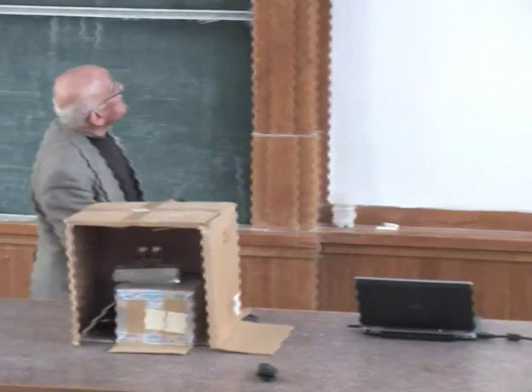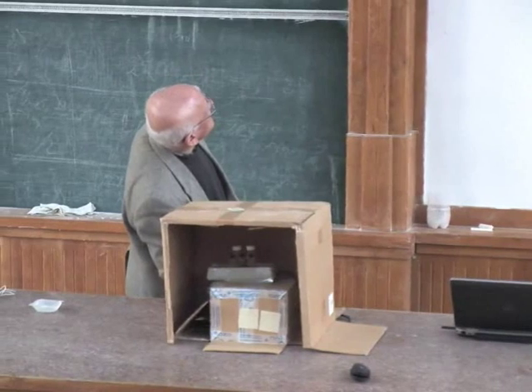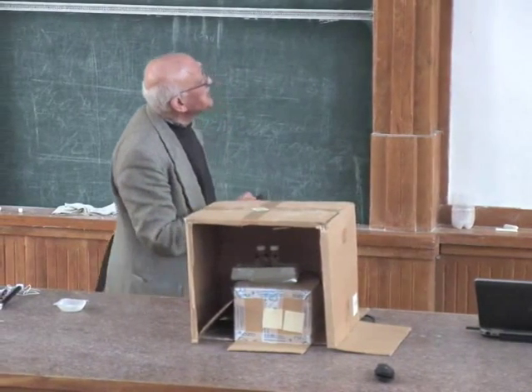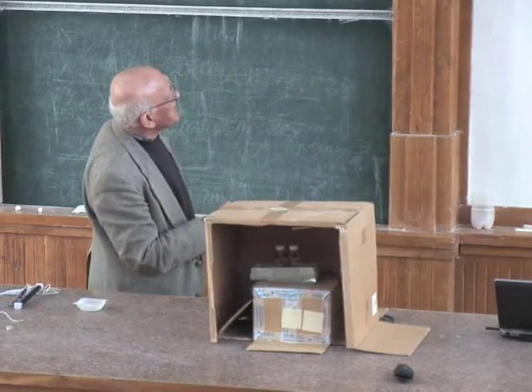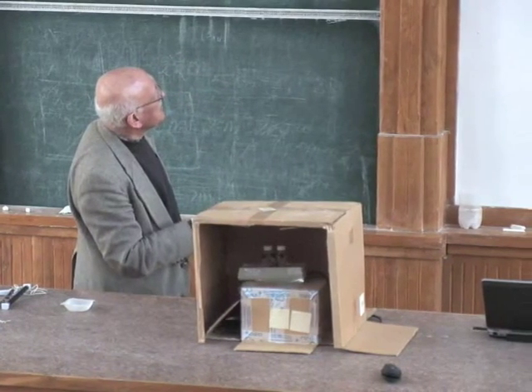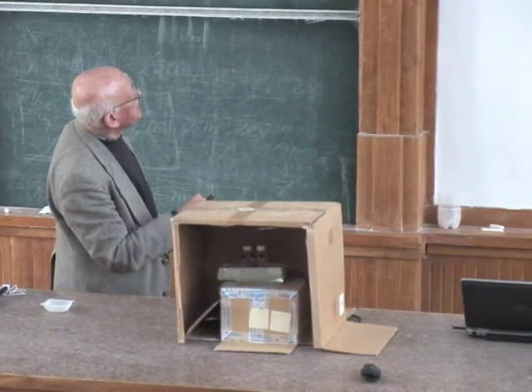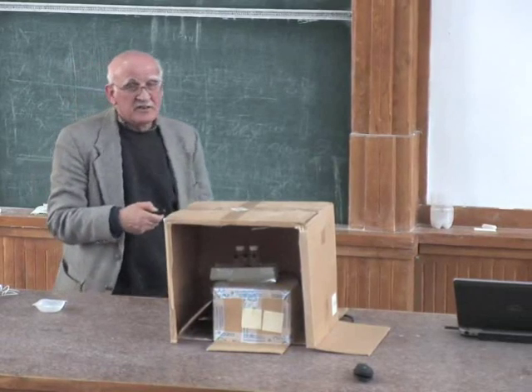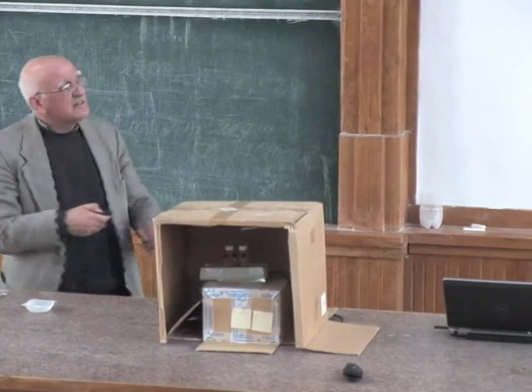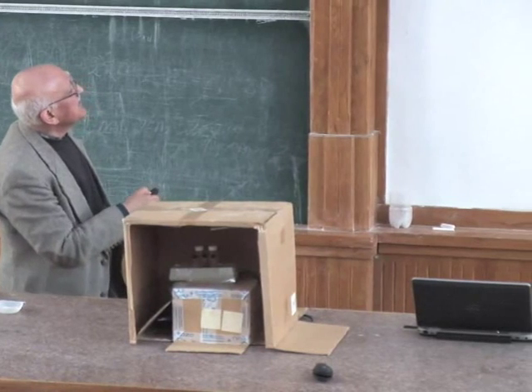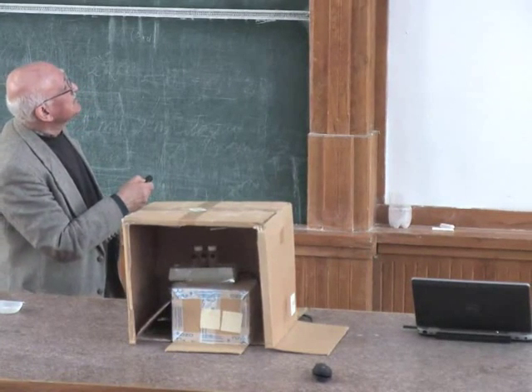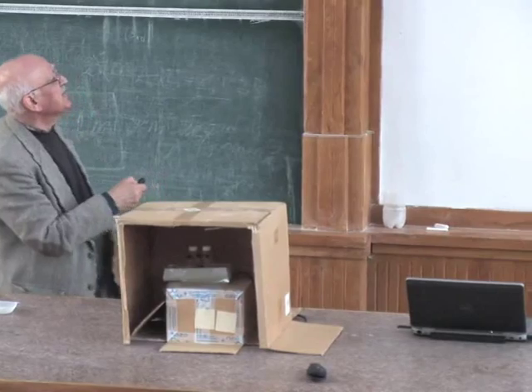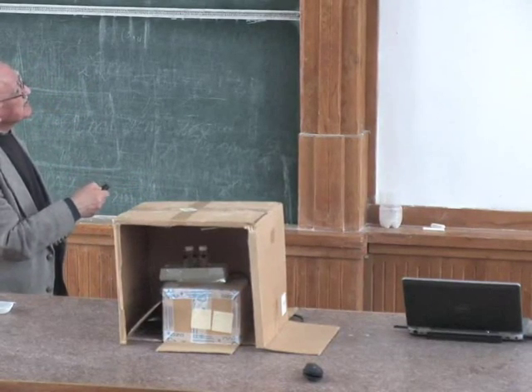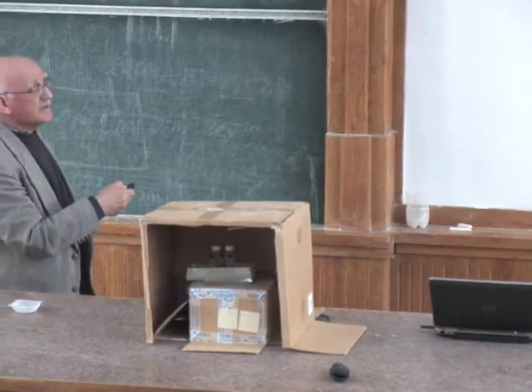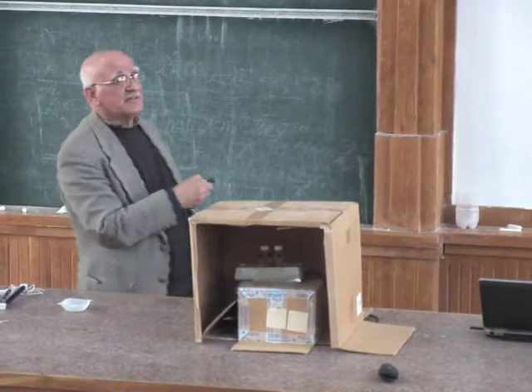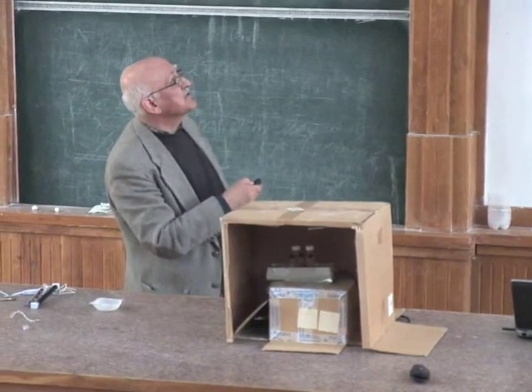You could put it inside of a memory. What is a flash memory? It's really a capacitor. Here's an electrode, an aluminum, on top aluminum, and in between glass. This is actually what we carry in our pockets. Very tiny. From here to there is like 50 nanometers, the thickness, and this wide is the same. So it's big. Transistors are much smaller than these units of memory cells.